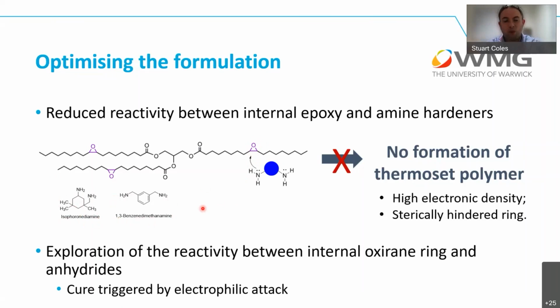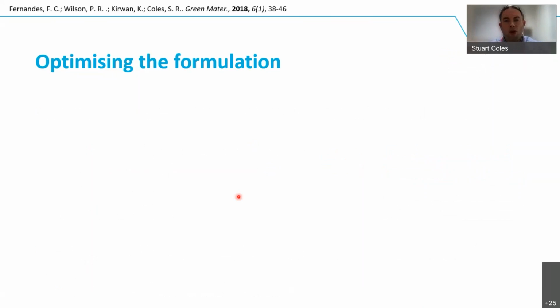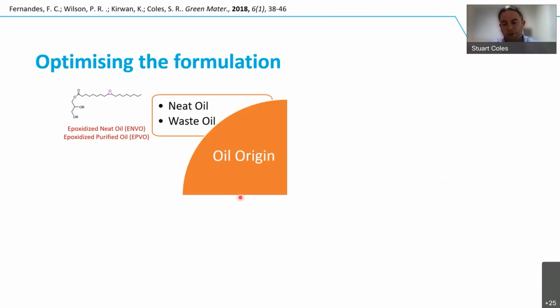So one of the things that we wanted to look at was whether we could change these cross-linkers and hardeners to something that would work better with our vegetable oils, while still maintaining reactivity with the DGEBA system as well, ensuring compatibility between the two. So we then started to optimize the formulation a little bit, and we did some design of experiments and statistical analysis to optimize for the best formulation that we could think of.